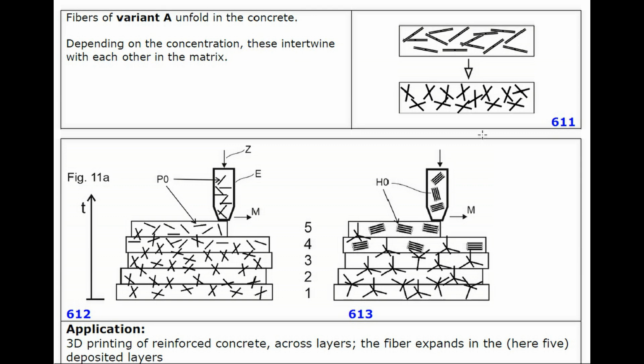Yes, it looks futuristic to use variant A to unfold it in the concrete in layers by robotic arms and pumped concrete. It needs time to expand in the layers. In the first or second layer it's already expanded, but when you lay it, actually in the layer number 5, it's not expanded because the glue needs time to dissolve in water. Same with the different version in picture 6.13.